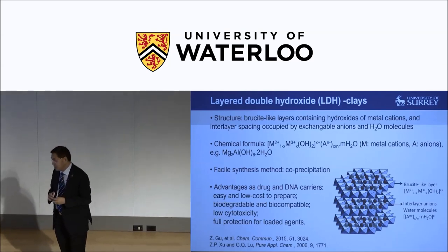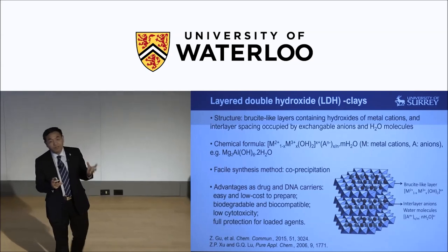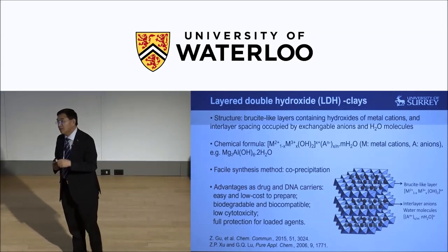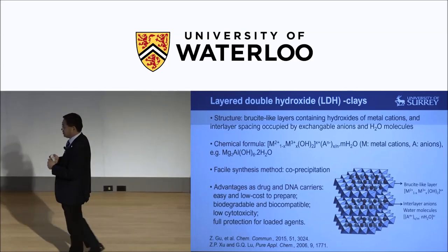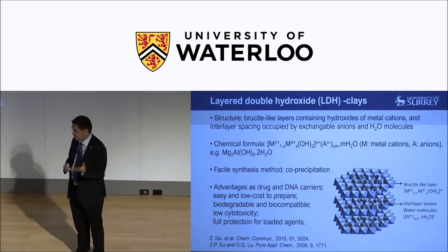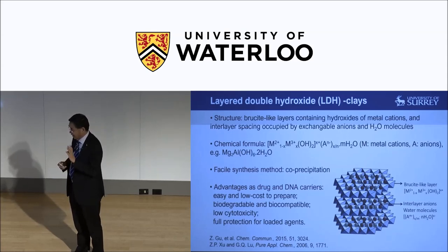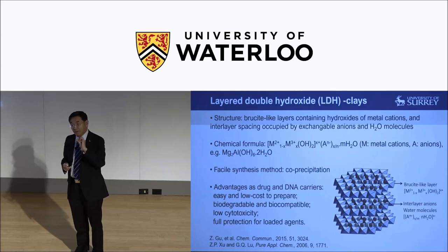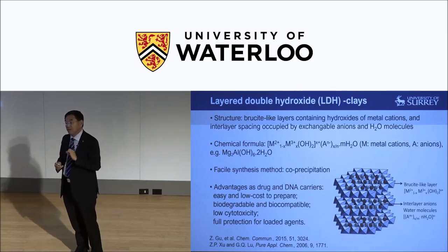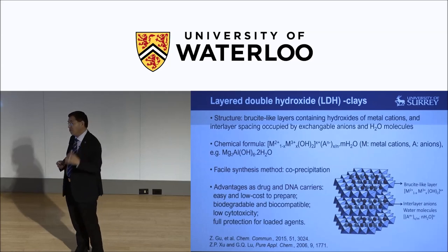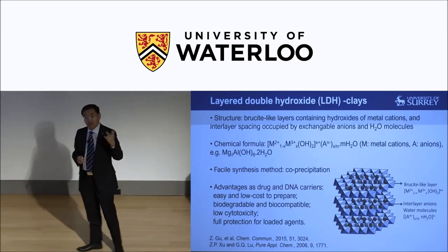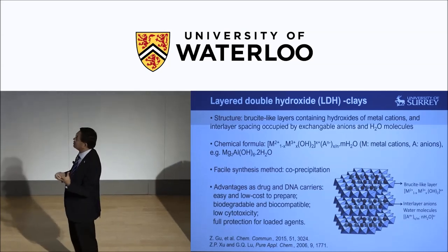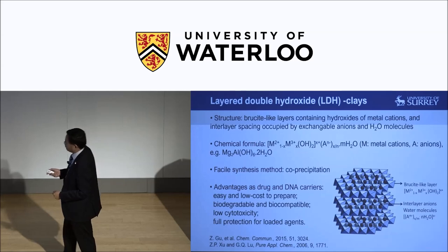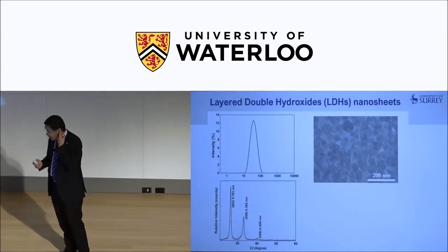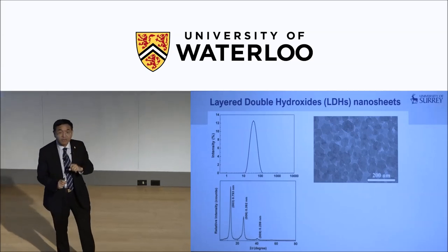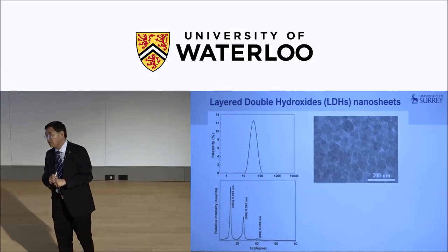We have been working in the last decade or so on a particular class of inorganic nanoparticles. It's called layered double hydroxide. Essentially, this compound is very flexible, very easy to make, and has low nanotoxicity and low cytotoxicity. It's an ionic exchanger, a clay particle that disperses in aqueous solution to become nanoparticles. And it's a perfect vehicle for drug molecules, siRNA and RNA, as a short-strand siRNA delivery vehicle. We've done quite a bit of characterization. Our contribution here is to synthesize the stable dispersible LDH nanoparticles.